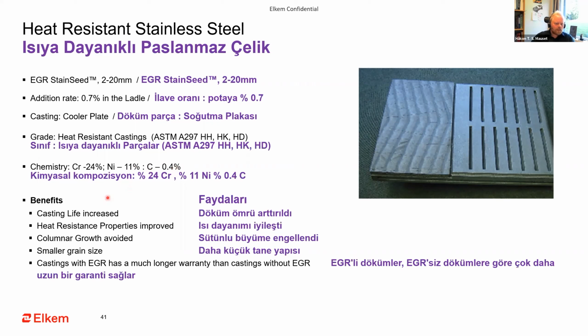But what this customer sees is that the lifetime of the components is increased when they are put into operation. Typically this can be used in cement production. So the lifetime of the component has increased, and the heat resistance properties are improved. They avoid columnar growth. They see a smaller grain size. And actually this customer gives a much longer warranty on the castings that are produced with EGR than the ones without EGR.